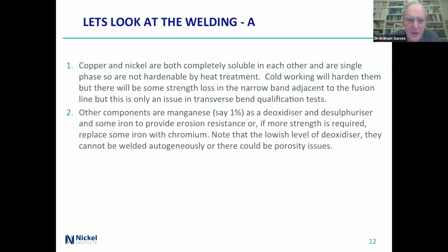The other components that are in there are a bit of manganese, about 1%-ish, as a deoxidizer or desulfurizer. So they're basically taking out oxidizing agents, and some iron to give you erosion resistance. Or if you want more strength, you can replace some of the iron with chromium. I'll show you the actual numbers in a few minutes. Because of the lowish level of deoxidizer, if you weld them autogenously, then you may have a problem. There might also be porosity issues at that point.